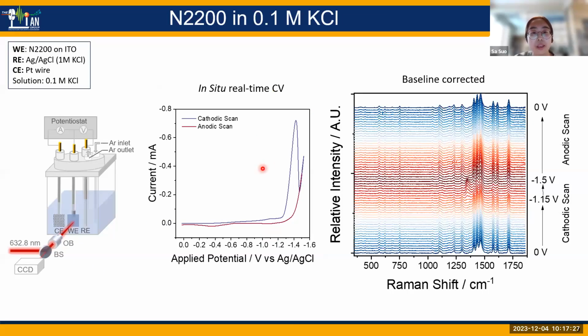So with that, we move to the vibrational spectroscopic measurement of a similar sample, but this time we use N2200 on ITO, and we just keep other conditions the same. We scan the N2200 from 0 to negative 1.5. We can see there are two reduction peaks with a 0.4 potential difference.